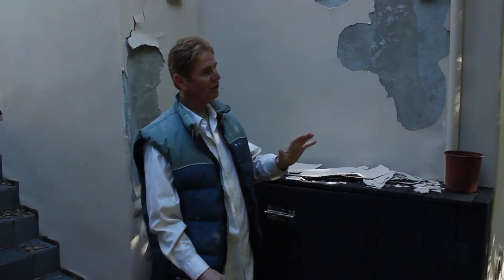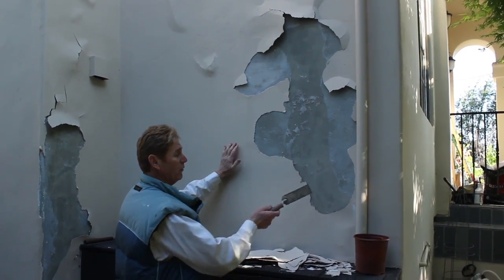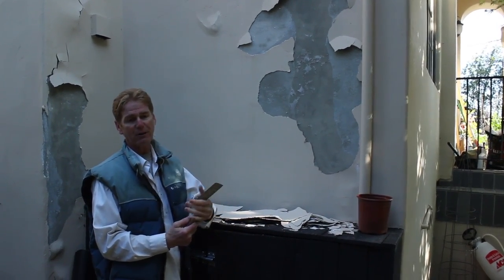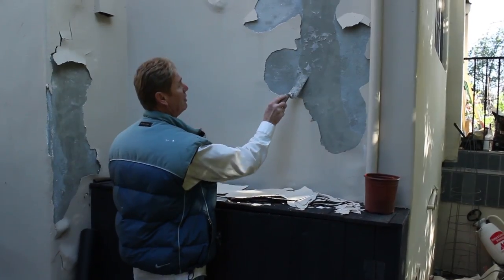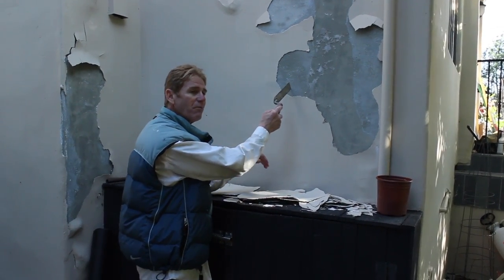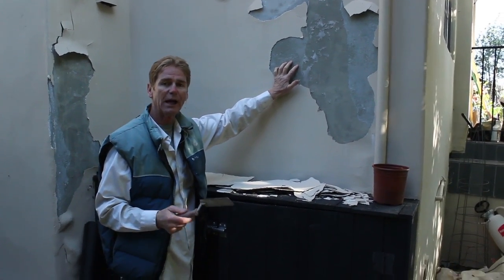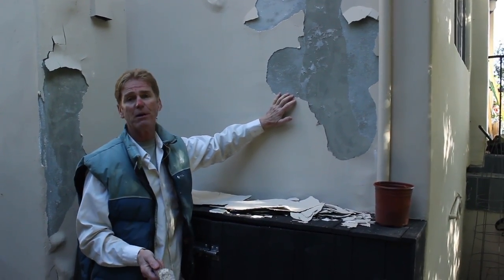The contractor did a great job - even got a weep screed following the stairs. I give that fellow a nine or almost a ten, because you can't watch everybody on the job. When we come back we're going to pressure wash this wall, and when I say pressure wash I'm talking about 3,500 PSI - a gas-powered pressure washer, because an electric pressure washer won't get the dust, dirt and grime off and won't micro-score this surface so our new finish will adhere. I'm going to use a bonding agent anyway.